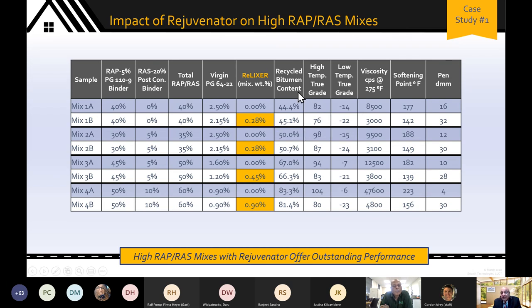So in this case, it's about 45%. You start increasing it to 50, 60, and Mix 4 has 80 plus percent of the total liquids coming from recycled bitumen content. So let's look at Mix 4A. Mix 4A, 80 plus percent of recycled bitumen content as a function of the total bitumen, 0% rejuvenator. Mix 4B, about 1% of rejuvenator, same 80 plus percent of recycled material content.